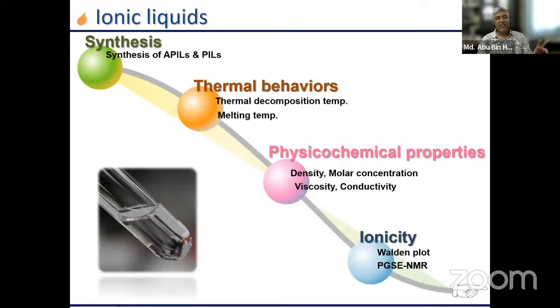So for ionic liquids, I have shown that there is a wide variation in structure and kinds of ionic liquids. Aprotic, protic, and even other ionic liquids can be prepared by different methods of synthesis. Thermal behaviors may be controlled. Physicochemical properties like density, molar concentration, viscosity, and conductivity may be changed. And ionicity, which is a very important parameter for ionic liquids and can be judged by the Walden plot or pulse gradient spin echo NMR, can also be varied. So this gives tunability in the ionic liquid structure and physicochemical properties.